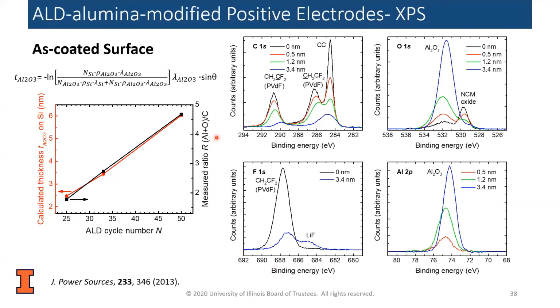So if you look at the ratio of the aluminum plus oxygen to the carbon, we found a region where the two of them were linear. So we could come up with a way that we could use this factor right here to relate it back to the thickness on the silicon wafer and get an estimate of the planar thickness that aluminum oxide would be. And so here are some XPS examples right here of the deposition. You can see, in fact, when we are depositing the alumina, that we are attenuating the carbon signal. We're building up an aluminum signal and also the aluminum oxide signal.